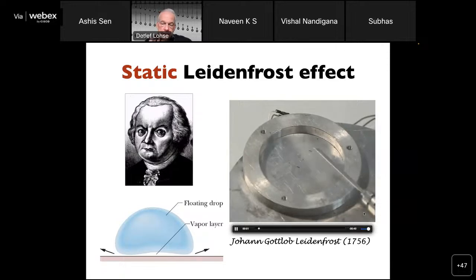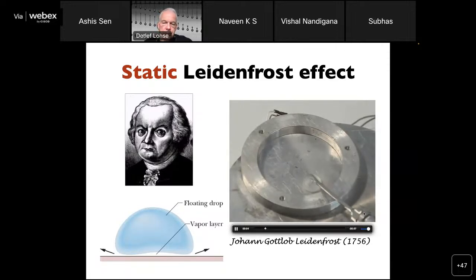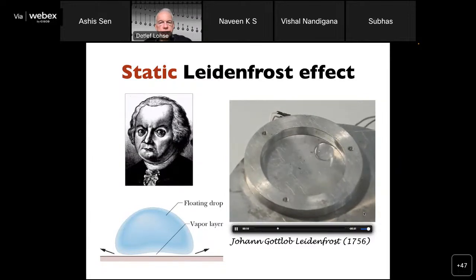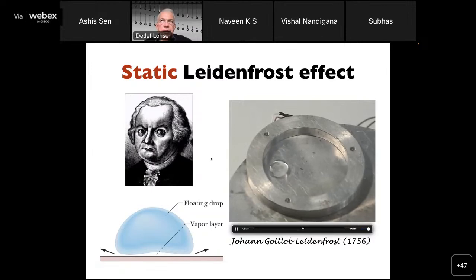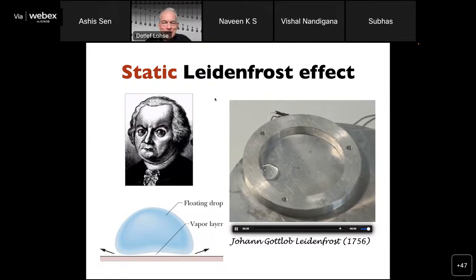And here you see what was done. So Leidenfrost took a droplet, put it on a spoon, and then on a hot spoon, and then let it float. And this droplet is supported by its own vapor. You see a sketch, floating droplet with the vapor, and then the lifetime is very large. In fact, what he did is he did lifetime measurements as function of the heating, and then he found this transition from the droplet in the contact mode to the droplet in the floating mode. So here you see Leidenfrost. Unfortunately, I didn't find a more friendly picture of him, well, he had quite some impact on the field and found this beautiful phenomenon.